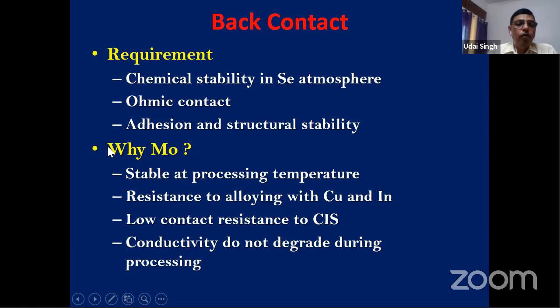So why moly? Why is only molybdenum used? Through different research, people have come to the conclusion that it is stable at the processing temperature, and resistant to alloying with copper and indium. It gives a low contact resistance to the copper indium selenide. The conductivity also does not degrade during the processing steps.